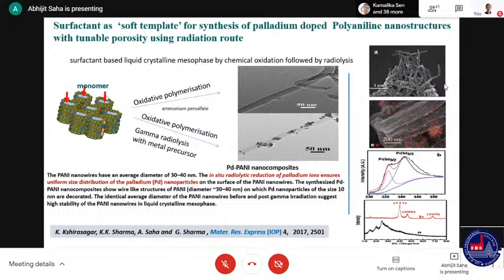This is one more example. This is where you can get composite materials with polymers. So the palladium is in polyaniline. This has a nanowire-like structure, where the particles are formed and uniformly distributed over the nanowire. This is also produced through the radiation route. And these are all characterized through XPS, X-ray photoelectron spectroscopy, then TEM and FESEM.